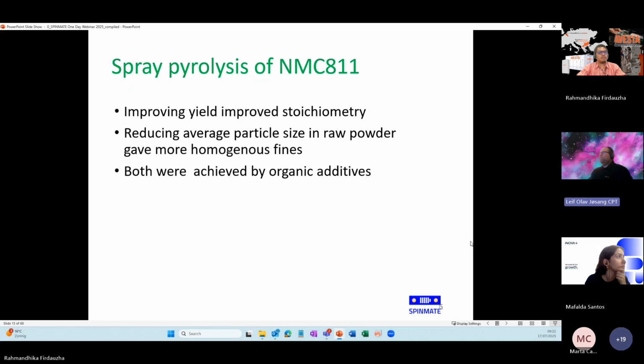So we also found that the poorer our yield during spraying, the worse the stoichiometry was. So when we managed to improve yield up to or towards 90%, and by using organic additives, we believe that we both produced a finer powder and a more uniform powder, so that the material we lost was no longer as nickel enriched. And we also lost a lower portion of powder, and both those help with the nickel loss.